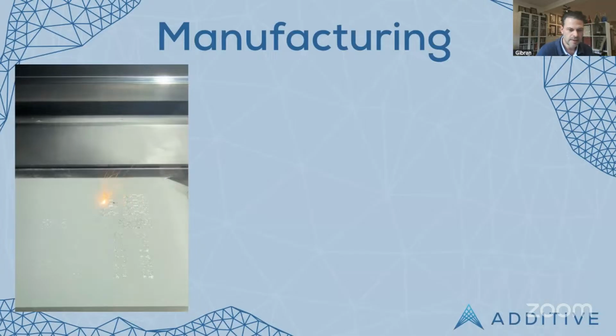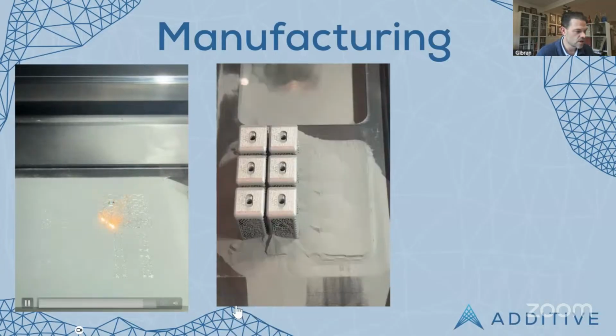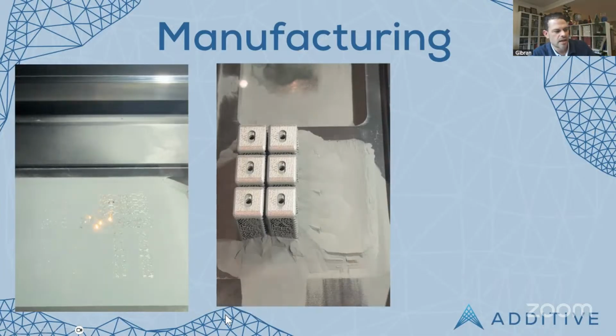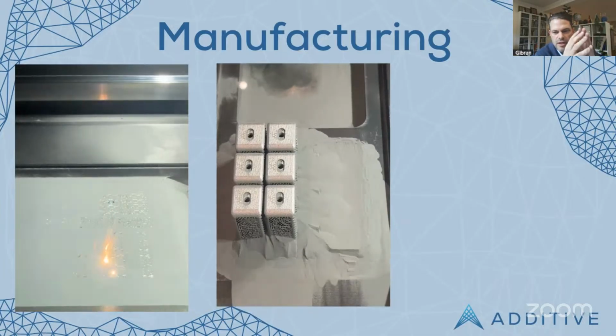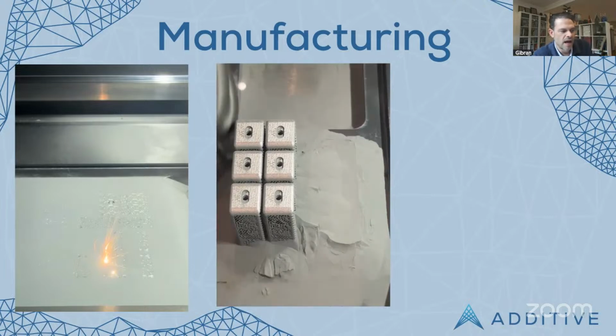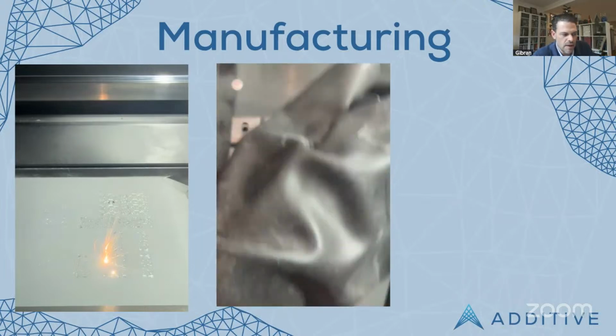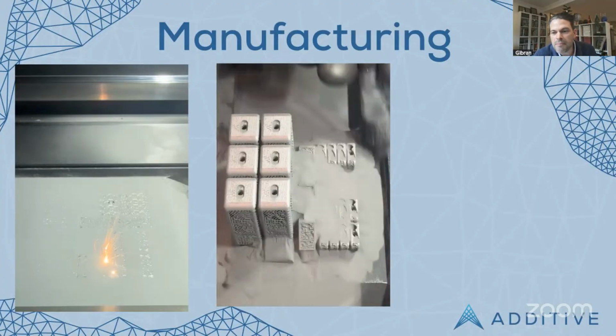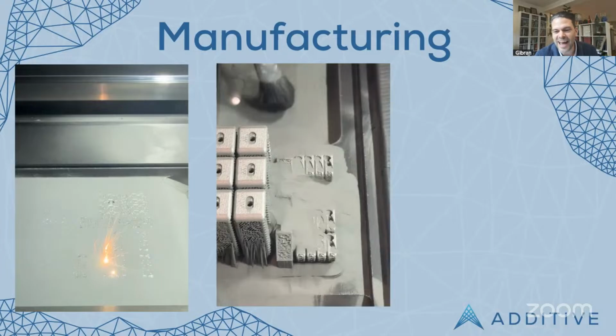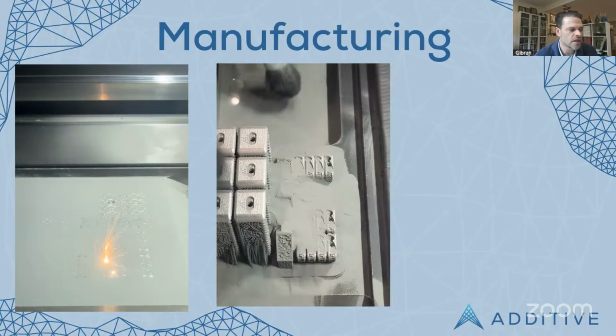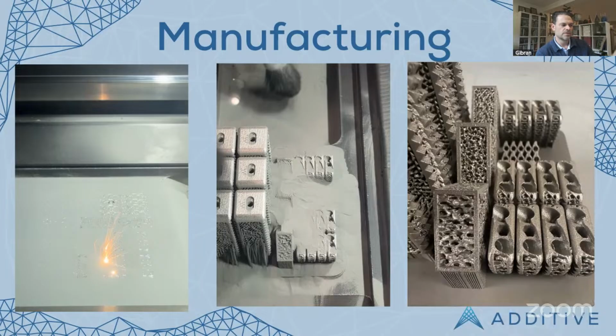And then those implants, so I'll come to this next slide here. When you're taking the bed of implants off, the rest of the titanium powder falls away. And then you're left with unprocessed, non-sterile implants. I just think about how additive manufacturing works, using lasers to melt titanium together, we can create these incredibly complex geometries and these lattice structures, which traditional manufacturing just can't do. So that's the process. That's the laser, then that's taking the powder off, and then they're the implants sitting on the build plate.